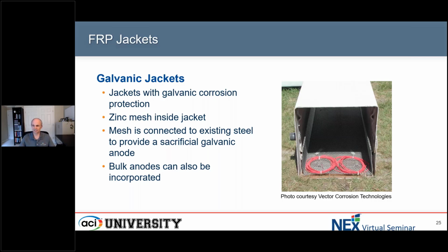You can also use these types of systems in combination with bulk anodes, where you're tying chunks of zinc onto the existing structure, again, to provide some galvanic protection to the existing structure. That photo that you see there, that is a fiberglass jacket that has a zinc mesh on the interior of it. Very typical style of a galvanic type jacket that is used for both protection and that sacrificial component to provide corrosion protection as well.